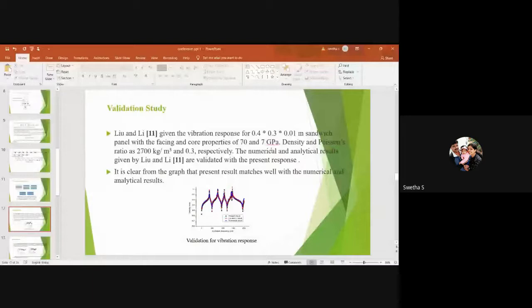So the numerical and analytical results given by Liu and Li were validated with the present approach that I have done. The validation study proves that all my results match well with the numerical and analytical results of the literature. In the results and discussion, the free vibration response of the sandwich panel is studied, after which the forced vibration properties are also calculated. Also, the vibration response of FGCNT reinforced polymer foam sandwich panel with CNT and porosity coefficient is shown.